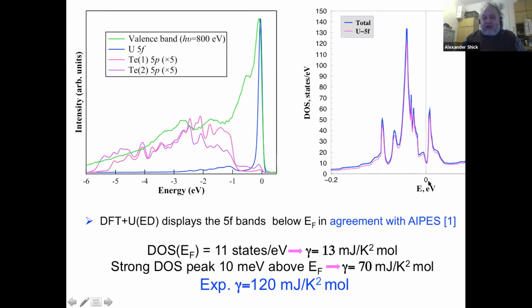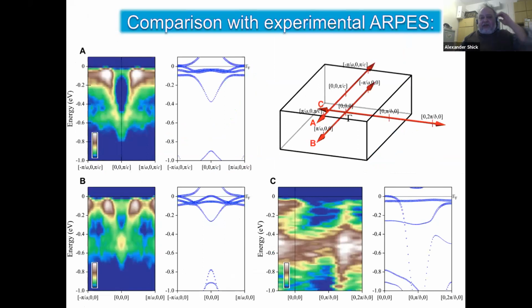And if I blow up my density of states near the Fermi edge, I see that exactly at the Fermi level the density of states is not so high, but then 10 meV above the Fermi level, there is a substantial peak, which gives me a gamma of 70 millijoules per Kelvin squared per mole, which is already reasonably close to the experimental value. Well, these are just band structure calculations. It means there is no dynamical enhancement or mass enhancement of the gamma, and there are no phonons. Therefore, this is already not really an unusual difference. So the next thing we did, we made a comparison with the experimental angular resolved photoemission.